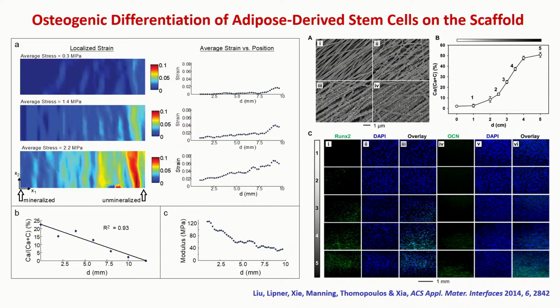And this is also consistent using another stain. In this case, we use osteocalcin. It's a protein that will bind to hydroxyapatite. It's a late marker for osteoblasts. So again, you can see the gradual change from position 1 to position 5. So this is just consistent. When you have more mineral coating on the surface, you are going to have a higher level of differentiation into osteoblasts. That's really what we expect to have.